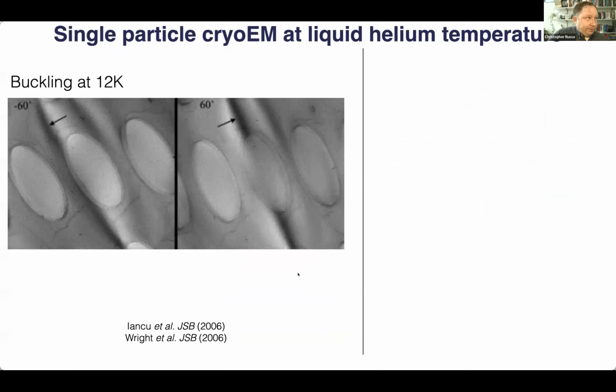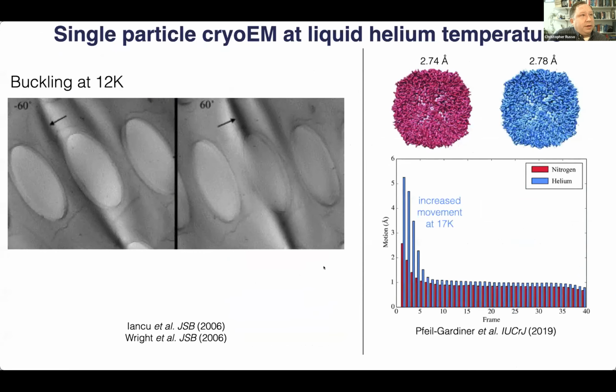The problem is that people have been looking at liquid helium for a very long time, and every time anybody's done a comparative study of the resolution or of images, they've found that things are always worse at liquid helium temperatures. This is a very recent one from Werner Kühlbrandt's lab, where they did apoferritin at liquid nitrogen and liquid helium, and they got basically the same resolution. And the interpretation of this was that the movement was actually worse at 17 Kelvin than at 80 Kelvin, but perhaps the images were better due to a reduction in radiation damage.